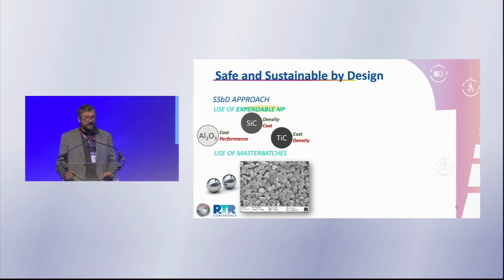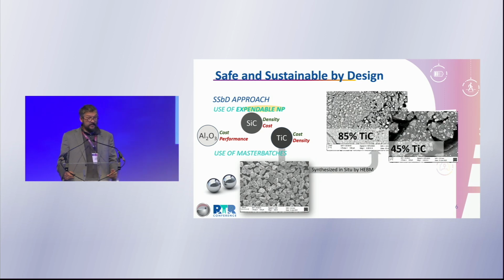So we concentrated on 3 kinds of nanoparticles that were there since the inception of the project. All of these had pros and cons. Silicon carbide has a good density compatibility with aluminum, but the cost of the nanoparticles is quite high. Titanium carbide, on the contrary, is problematic from the point of view of density compatibility, but cost is lower because we managed to develop a process to make the titanium carbide particles directly in the metal matrix.